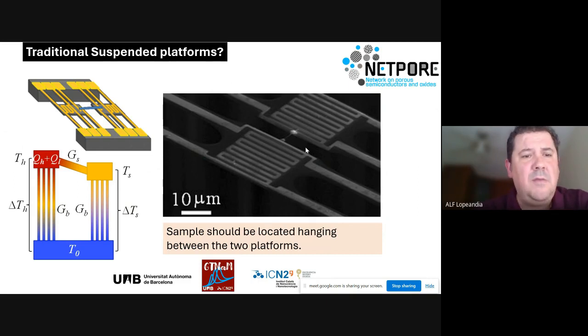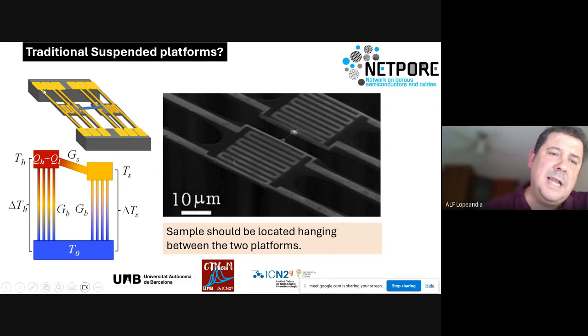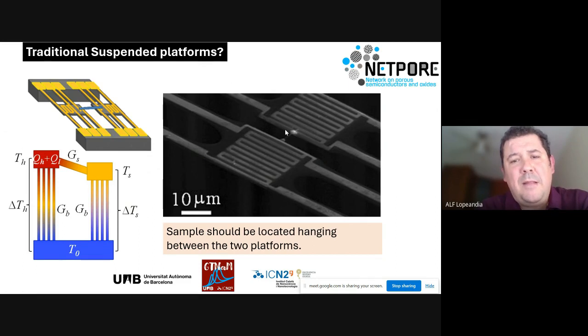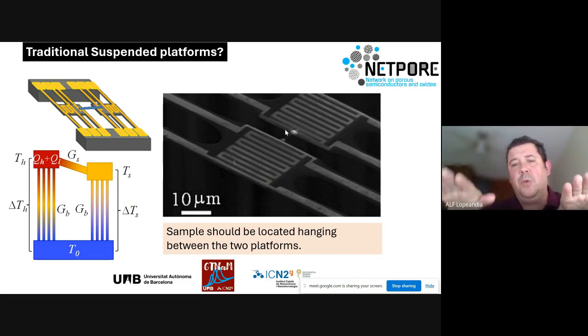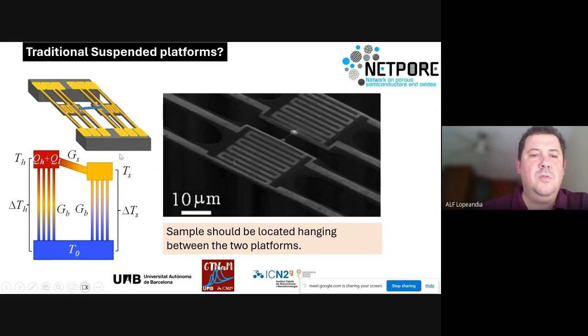And then the idea is that the platforms are slightly thermally coupled to the silicon frame, to the bulk silicon frame, and we can thermally actuate through the resistive coils, heat up one platform and then measure the temperature rise of the other platform, and then estimate the thermal conductance. I will not go into too much detail because of the question, but it's pretty simple. You can solve the heat transfer equation, and through the temperature rises, we can extract the thermal conductance of the sample, of the nanowire.